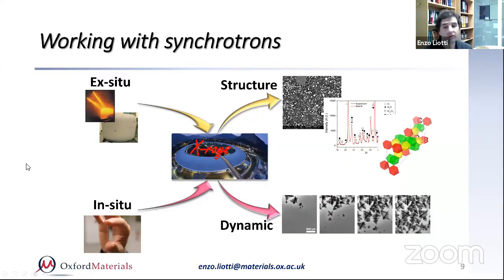X-rays are very powerful tools for material scientists, especially for metallurgists. If we use a synchrotron, we can use X-rays to study the structure. Studying the material ex situ is when you study the material as the final product. So for example, you do a casting and then you cross-section it and look at the microstructure with microscopes. That's an ex situ experiment. So you do it after, right? When you're doing an in situ experiment, essentially you're looking at a process while it's happening. So that allows you to catch the dynamics of the process, which is very important, especially in very dynamic phenomena such as solidification.